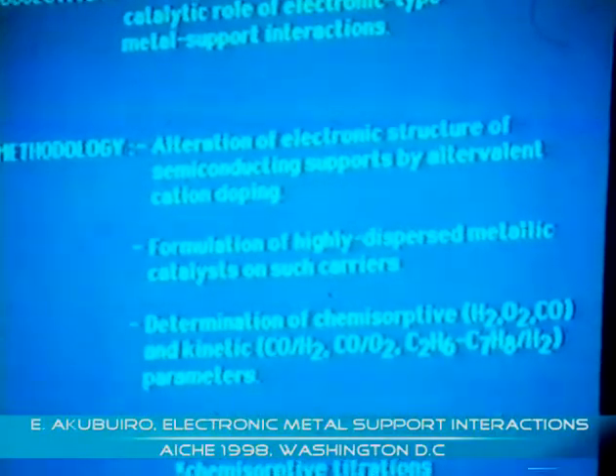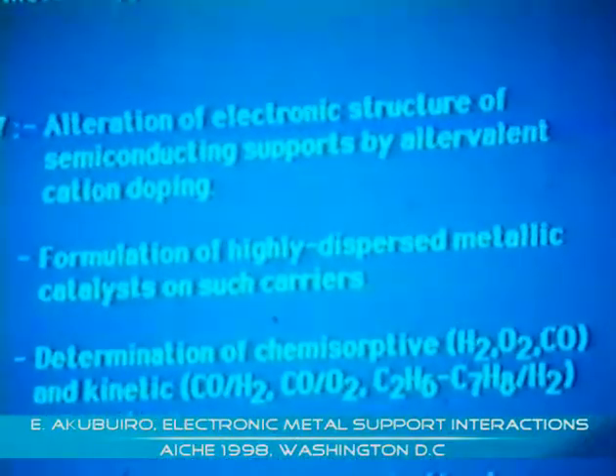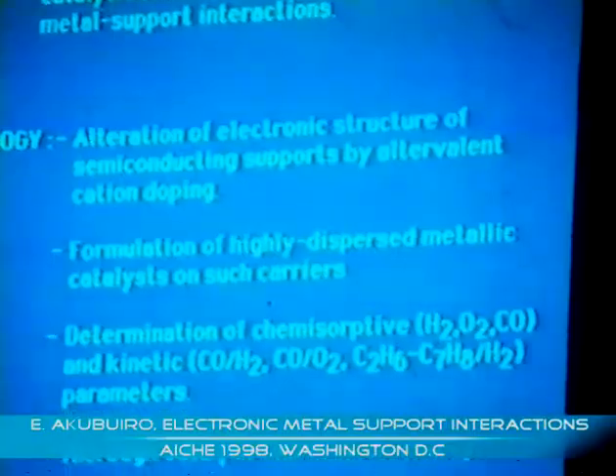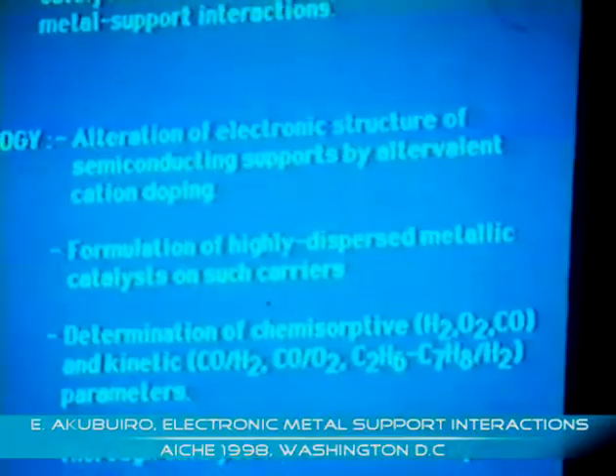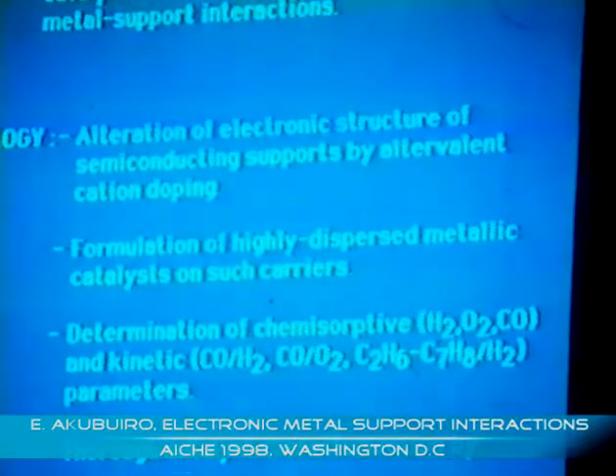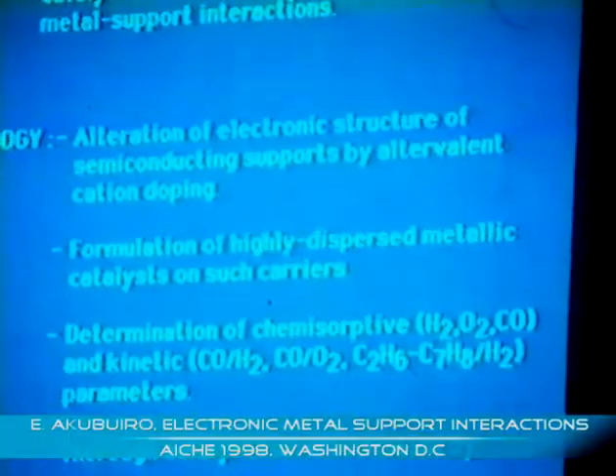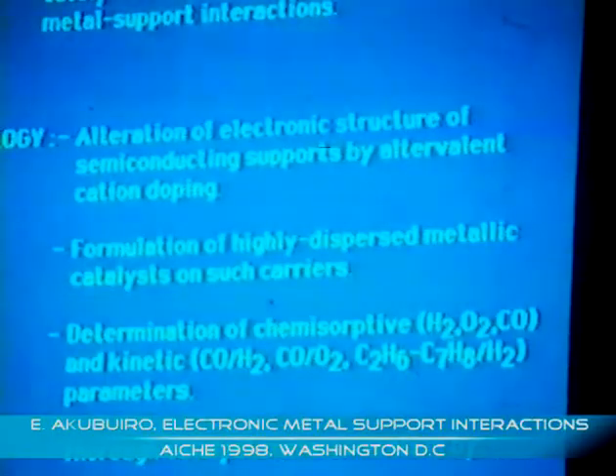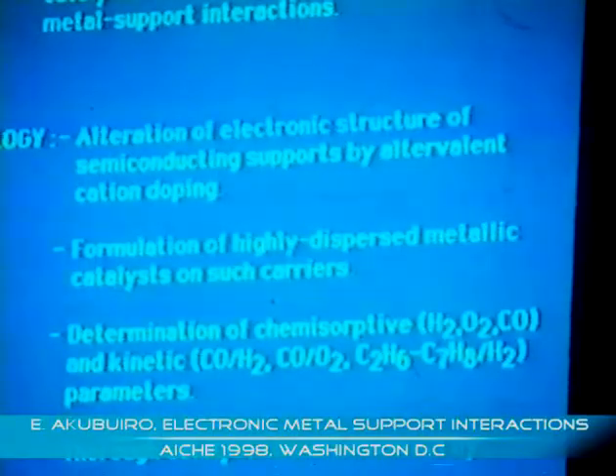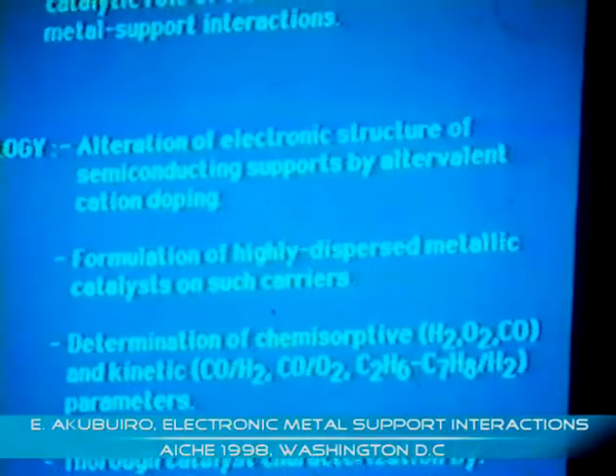The methodology followed in this investigation involved alteration of the electronic structure of the semiconducting support, titania, by aliovalent cation doping, the use of these doped materials to formulate highly dispersed metallic catalysts, and determination of the chemisorptive and kinetic parameters over these catalysts under different conditions. The catalysts used in this study were characterized by chemisorptive titrations, by measurements of the electrical conductivity and activation energy of electron conduction, by temperature programmed desorption, ESCA, FTIR of adsorbed CO, and TEM.